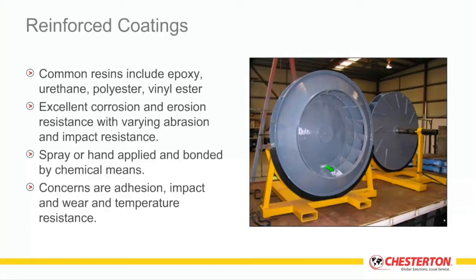Some of these systems can have relatively high ceramic reinforcements, as much as 85 to 90% on a weight and volume basis, and that gives you an extremely high wear resistance, essentially the same wear resistance as ceramic tile, but you've eliminated the seams and the grout lines that you might see with ceramic tiles as well as with rubber-based systems. So you get the benefits of the rubber and the ceramic without the negative attributes.